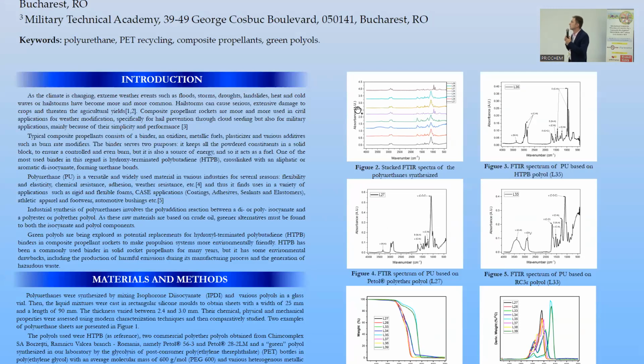The FTIR revealed the chemical structures that we expected. All the polyurethanes had peaks associated with carbon-nitrogen and nitrogen-hydrogen bonds. The commercial polyether polyols and the green polyol had the carbon-oxygen-carbon ether bond that we expected, while the HTPB had unsaturated carbon-carbon double bonds.